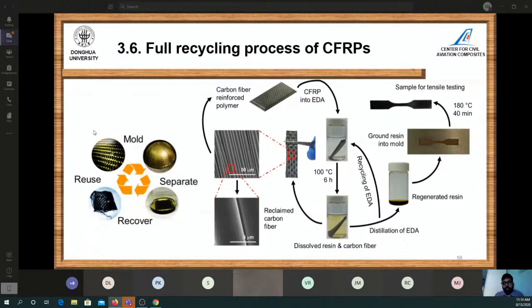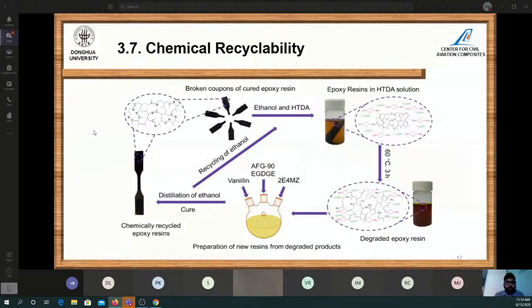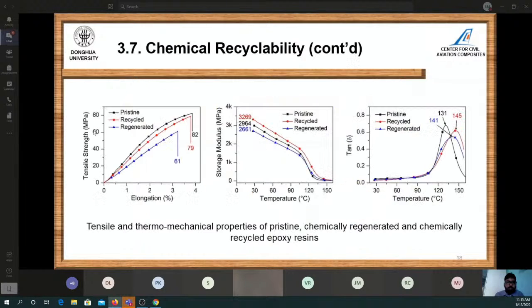Also, we boiled out the solution, and the powdered resin was tested for its tensile strength. We also tested the chemical recyclability of the resin by adding more monomer to it. In this chemical recyclability scheme, the broken coupons of epoxy resin were dissolved again in HTDA, and more vanillin and AFG90, the epoxy resin, and the catalyst were added. The distillation of ethanol was guaranteed, so that it can be a fully closed loop recycling.